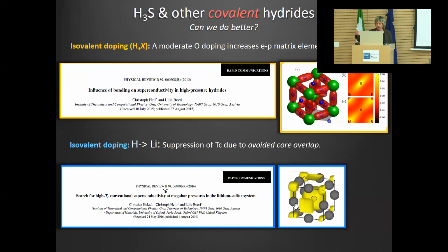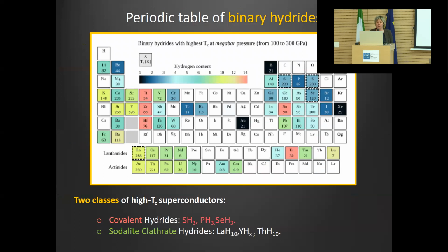So this is indeed, it turns out that to find a high Tc superconductor in this lithium sulfur system, you have to apply much larger pressure and search much harder than with the corresponding hydrogen phase diagram. Okay, so we have seen the first class of superconductors, the covalent hydrides. We now move to the second class.